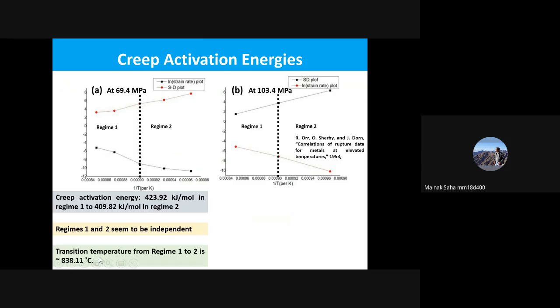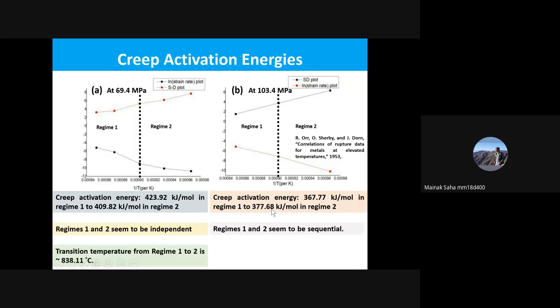But now, when we go to a higher stress level, 103.4 MPa, it is observed that the creep activation energy decreases from 423.92 to 367.77 in regime 1, and in regime 2 it again decreases quite a bit, to around 377.68 kilojoule per mole. Now the regimes 1 and 2 seem to be sequential. Why? Because there is no discontinuity in the slope at the transition temperature, and the transition temperature is found to be 825.90. It has also decreased quite a bit when we go to higher stress levels.